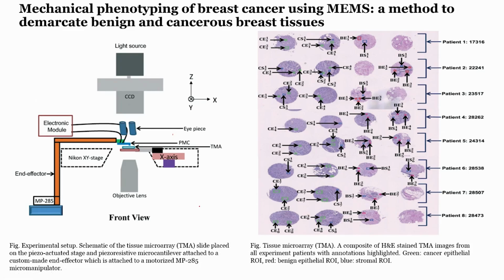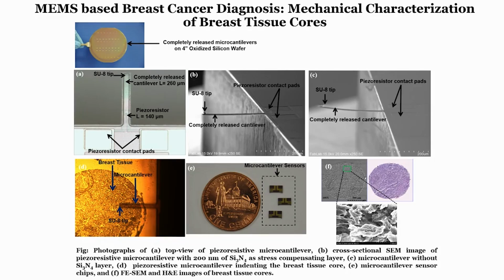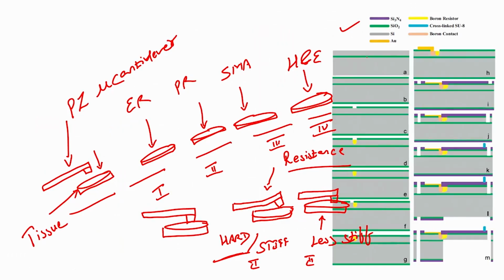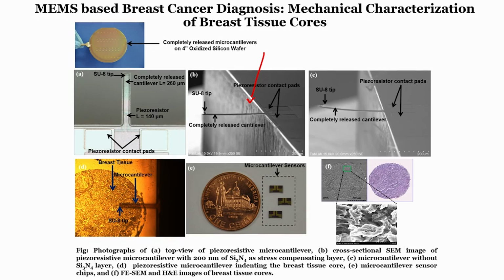This is an inverted microscope, there is an eyepiece and an XY stage. We have used Nikon. The MP285 is a micromanipulator, so you can indent the tissue with micron precision. There is an effector, and the piezoresistive cantilever will look like this if you fabricate it properly. If you miss a step, for example, in this process flow we have seen that there is silicon nitride that we are using. The silicon nitride will work as a counter stress when we use silicon dioxide. If I do not use silicon nitride, then you can see that the cantilever is bent.